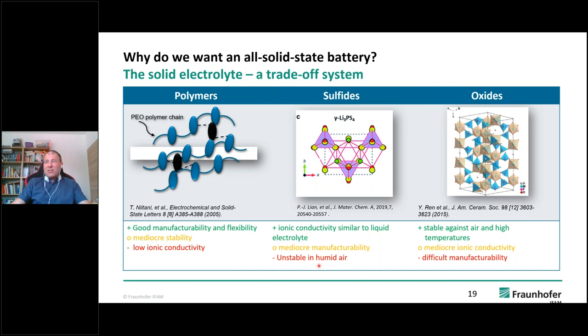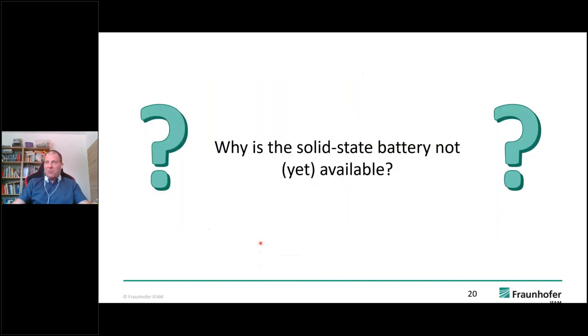The sulfides are not stable in humid air because they react with water, forming H2S, hydrogen sulfide, which is flammable and also toxic, which is also not nice, and even goes a little bit back to the problem that we have with liquid electrolytes. And polymers are good to build, but they have the lowest conductivity of them all. So as you can see, it is not decided which material will actually be inside of a solid electrolyte. So we will have to see which makes the run. I cannot tell you at the moment, but all materials are actually under investigation.